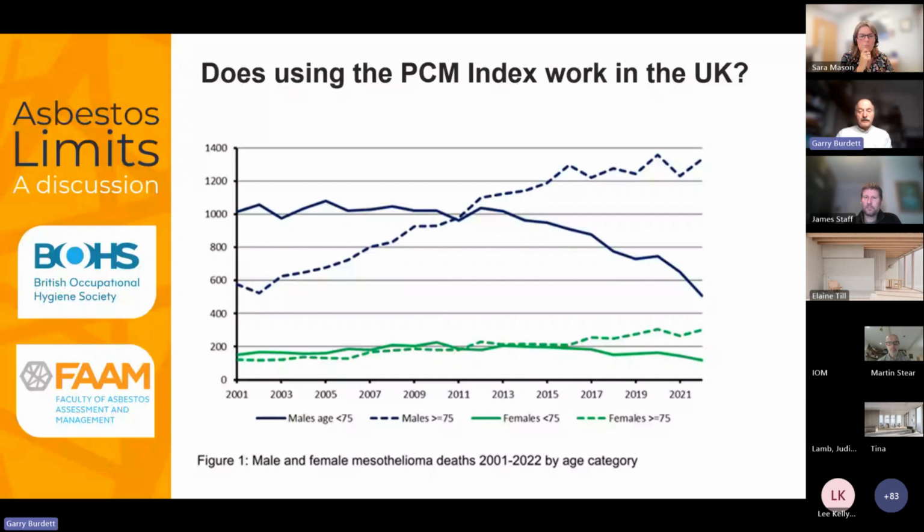Going back to the European directive, I think it was explained very well. If we look at the last bit, it's changing to an electron microscopy method, which can count long, thin fibers, possibly not counted by PCM. Now, this isn't very defined, so I use the term electron long fibers per millilitre of air. That's any fiber greater than 5 micron long of any dimensions. I'll come back to that.